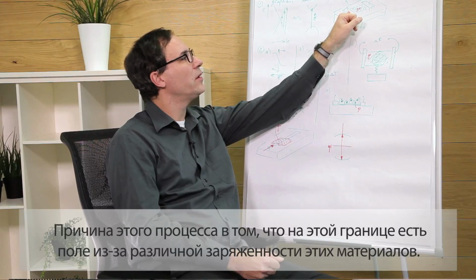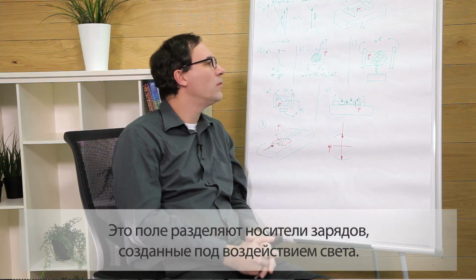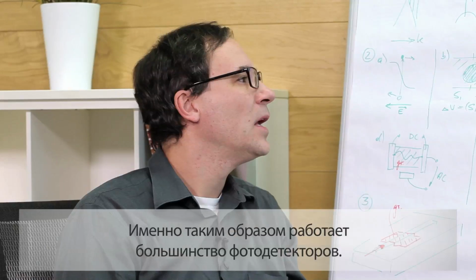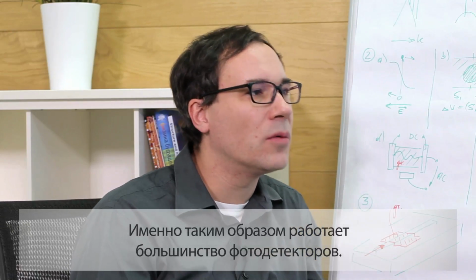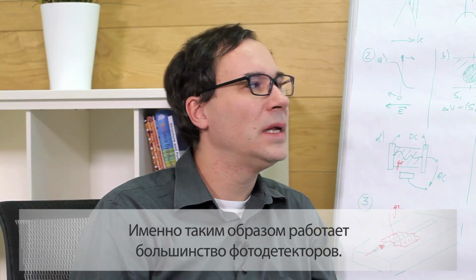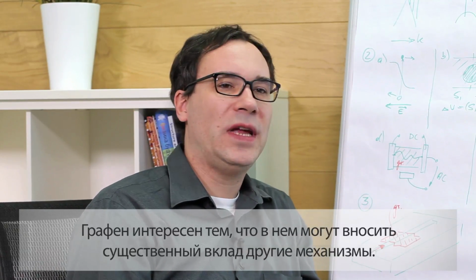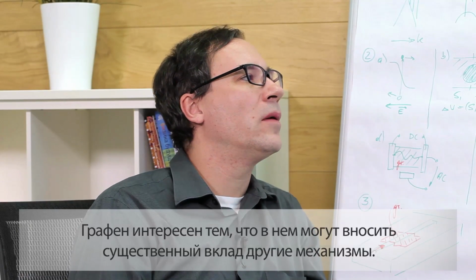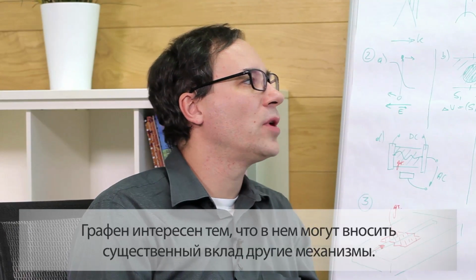The reason for this process is that you have some built-in field at this interface because of different charging of those two materials. This built-in field separates the photogenerated carriers just by the electric field that's built in there. Now, this is actually the way most photodetectors work. What's special about graphene is that there are also other mechanisms that can contribute a lot.